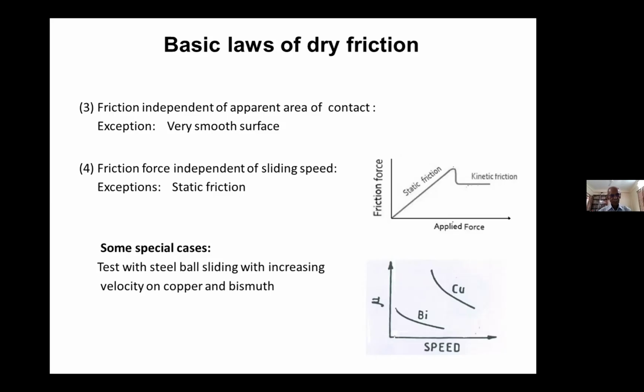So to state categorically that the frictional force is independent of sliding speed has to be taken carefully. Then there may be another point: if we take two steel balls sliding with increasing speed on copper or bismuth, then it has been found that the coefficient of friction drops as the speed increases. The experiment was usually done by allowing the two balls to slide along an inclined plane made of bismuth and an inclined plane made of copper.